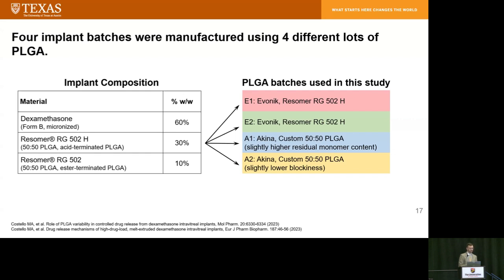So Akina specially engineered these PLGAs to be slightly different in blockiness. They're also different in some other properties, such as the residual monomer content. And then we tested the 4 batches for all of the critical quality attributes that I discussed earlier. They looked the same. The key difference was just the PLGA, the initial PLGA used to manufacture the 4 batches.